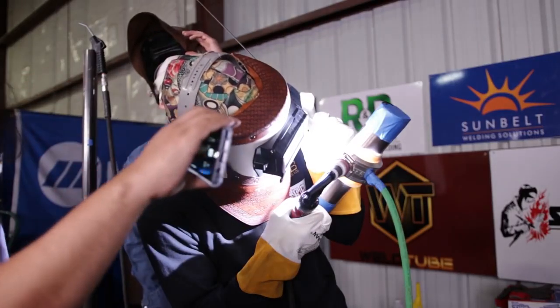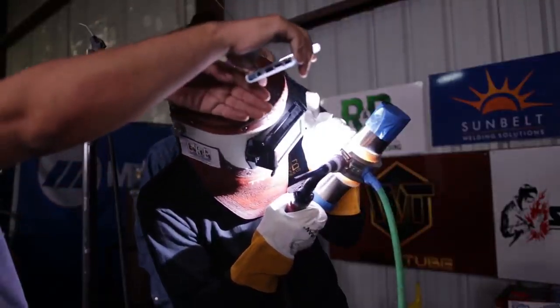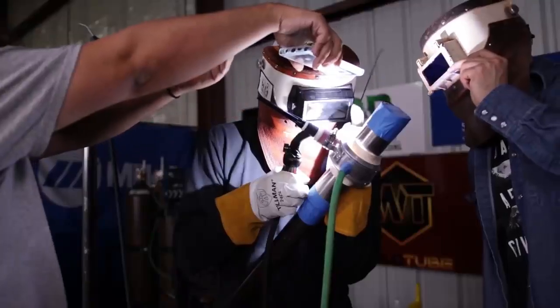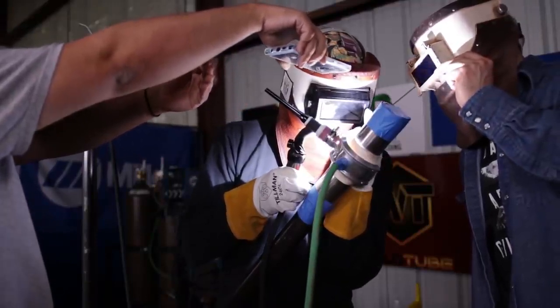It depends on what welding technique I use, whether a dabbing technique or a break surface tension technique. In this video, I'm using a dabbing technique. I'm using enough current that I can open the keyhole and carry a liquid weld puddle. When I apply a solid mass, which is the filler metal, and dab into the liquid weld puddle, it in turn chills out. The weld puddle has to break down the solid mass being added to it. So dabbing is breaking surface tension on the filler metal's own accord. I dab material into the weld puddle, it momentarily chills out, and I get solidification, and that repeats over a distance.